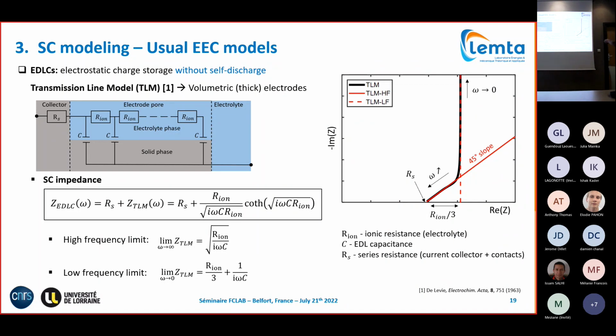Here you see the typical associated Nyquist plot. It is characterized by a vertical line at low frequencies, corresponding to the capacitive charge storage. At the highest frequencies you have a 45-degree slope with an intercept on the real axis, the series resistance. This 45-degree slope is associated with ion conduction along the pore space. This means that if you observe a 45-degree slope in the spectrum, it is directly linked to the volumetric character of your electrodes, with ion conduction inside the electrode thickness.